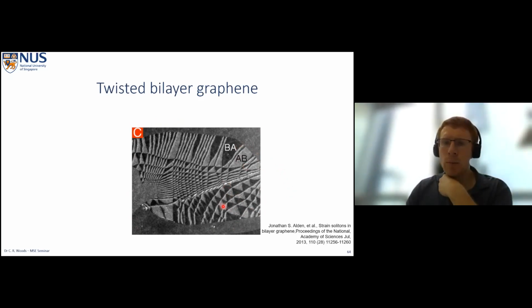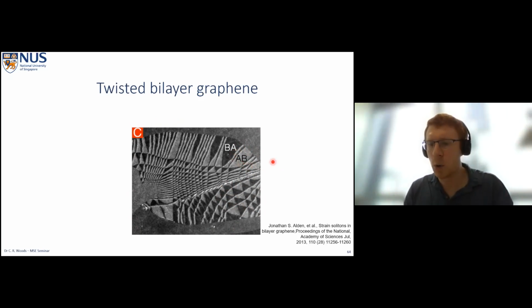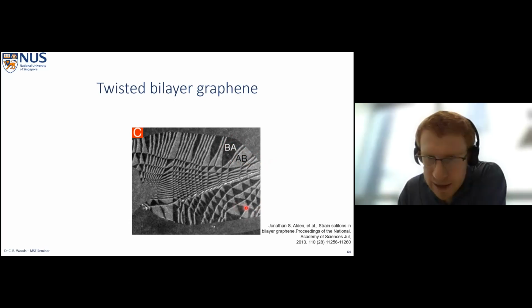So we know that we produce these triangles when the interface between the 2 crystals tries to reorganize, tries to create a system where it has preferential stacking in as much of the interface as possible. The only problem it has is that the BA and AB stacking configurations for a parallel interface have exactly the same energy. So when they compete over which takes up more of the interface's area, because they have exactly the same energy, they end up taking up exactly the same amount of the area. And so that's why we see these triangular domains. So one of them is AB and one of them is BA.